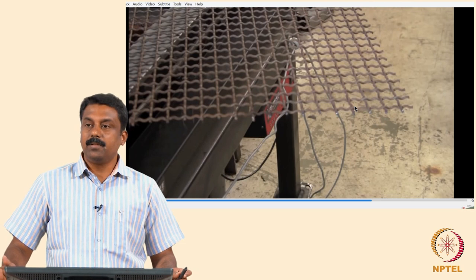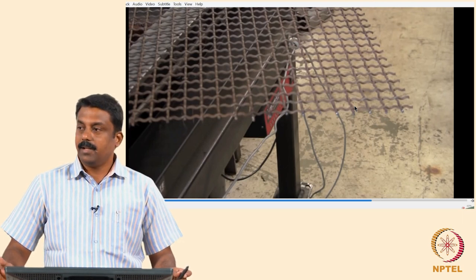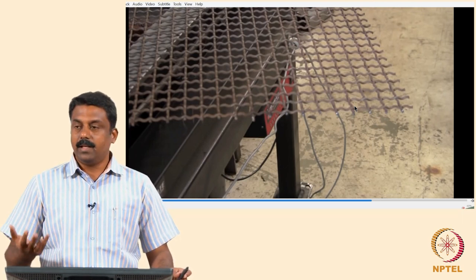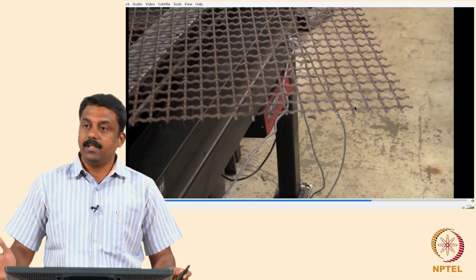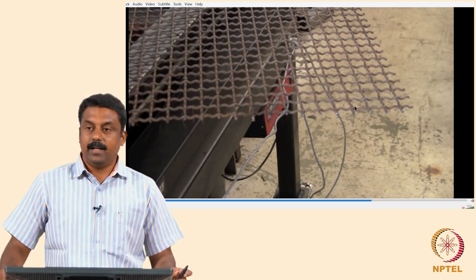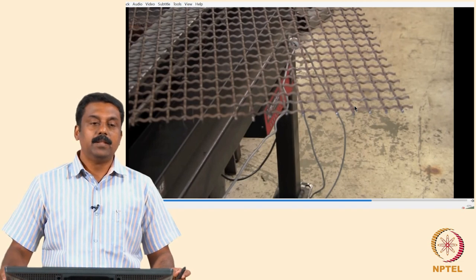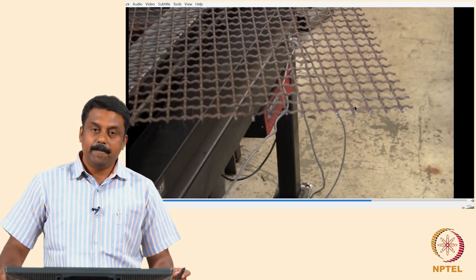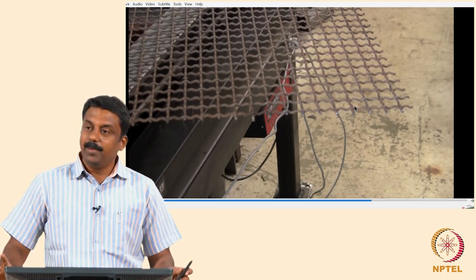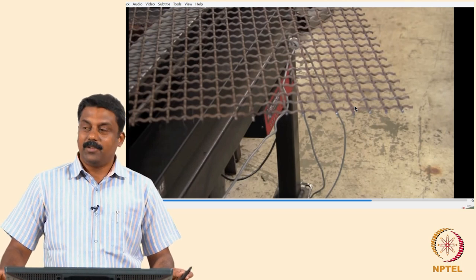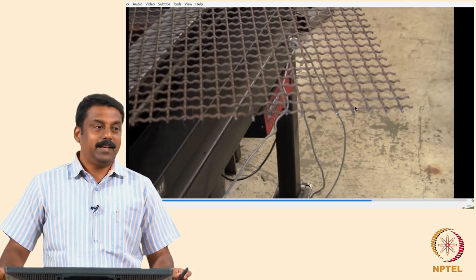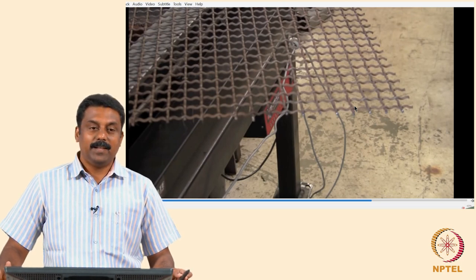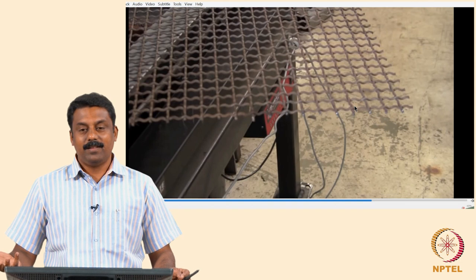Okay. Similarly, using a pilot arc, you can reduce the heat input, because the pilot arc can be struck even with 20 amps, even less than that. Even a micro plasma can be generated. So is all this possible by only one trick? What is the trick? By constricting the arc. Okay. So, how did we arrive at this? By understanding the physics of the arc.